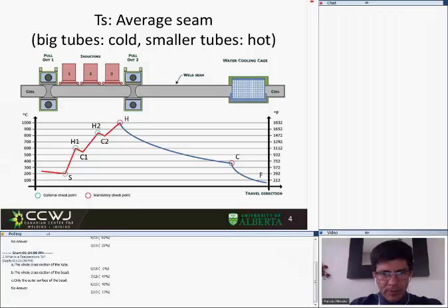But I made the numbers changing this temperature from 100 to 200, and it's a lot. The difference in distance between using a temperature of 100 Celsius degrees and using 200 Celsius degrees is very big.